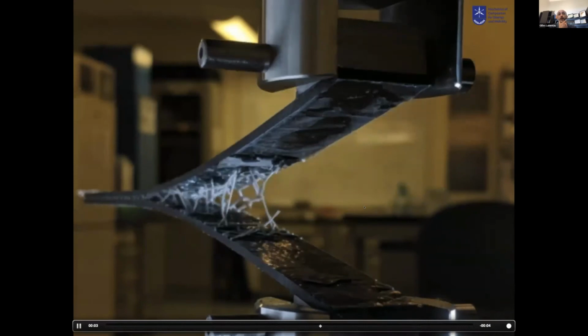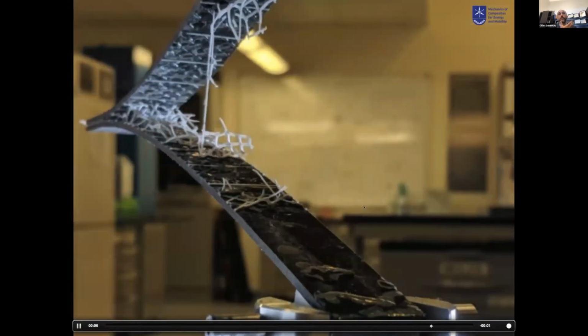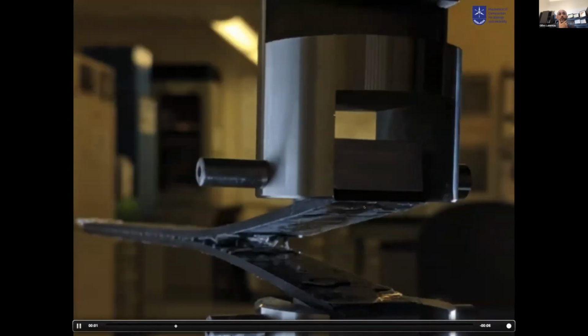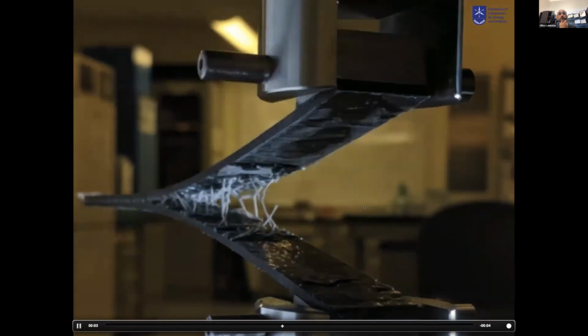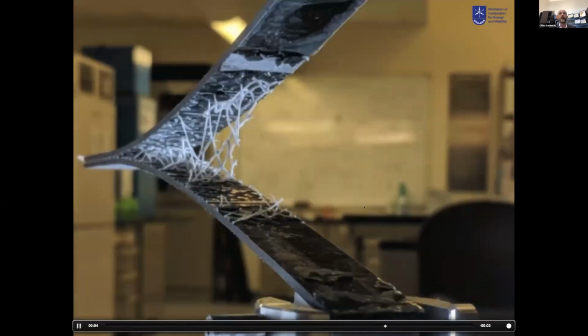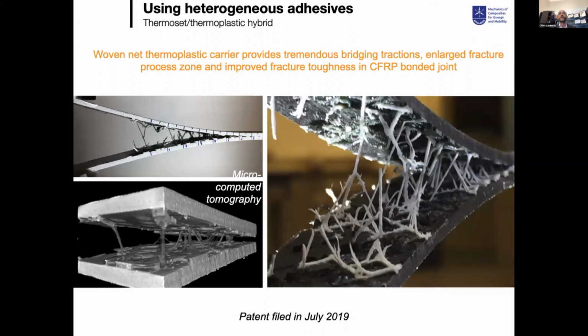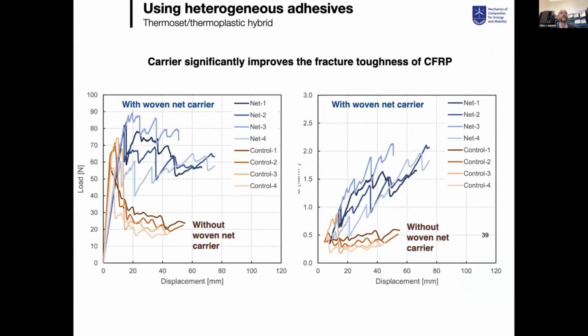That means if you engineer this properly, you give enough freedom to the thermoplastic to stretch and to expand and to dissipate energy during the delamination. And this is something that, when you see this, is going to give a huge improvement in your curve, because in orange here, you have the original curve without thermoplastic carrier. And in blue here, you have the modified curve in which you modify in a correct way with thermoplastic inclusion, and you can greatly increase the performance of your system.